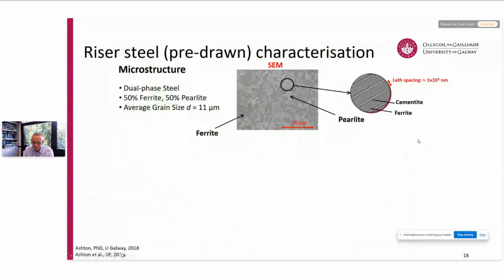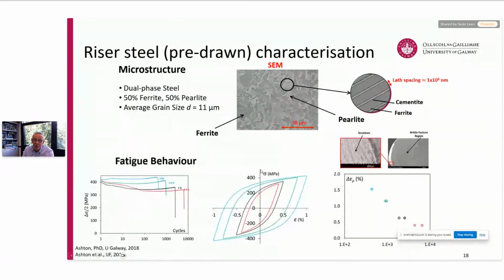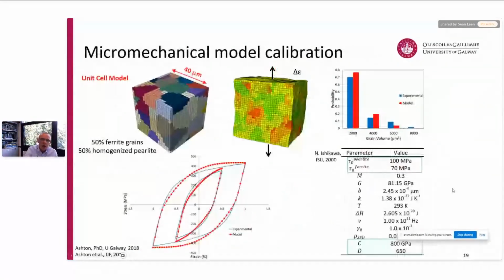So we're starting to see an effect of the microstructure from these models in terms of trying to capture this contact size effect. Then we've gone on and characterized the microstructure in these basic dual phase ferritic pearlitic steels. We've characterized the microstructure in a bit more detail, as you can see here. And then we've developed more complex models, which are basically dual phase models with ferrite and homogenized pearlite, the unit cell model in the top left.